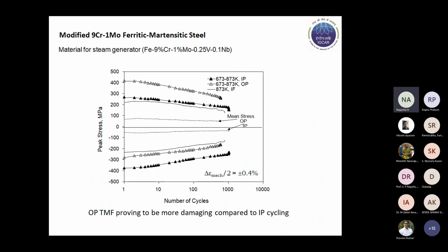Coming to the steam generator material, the ferritic martensitic steel, this 9 chrome 1 moly, 0.2 vanadium, and a little bit of 0.1 niobium steel. Due to higher thermal conductivity and lower thermal expansion, this is the material normally preferred for the steam generator components of the FBR. In this material, it gains strength mainly through three important factors. One is the martensitic structure, another is the finely distributed carbide particles, and another is the high dislocation density that is characteristic of these materials.